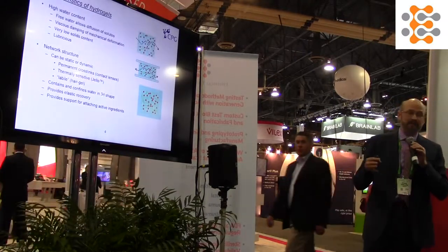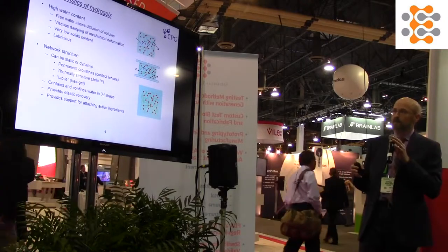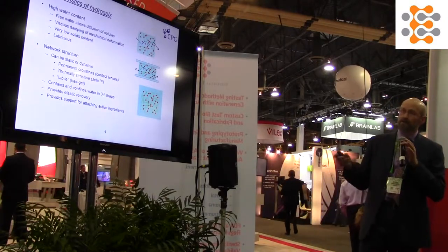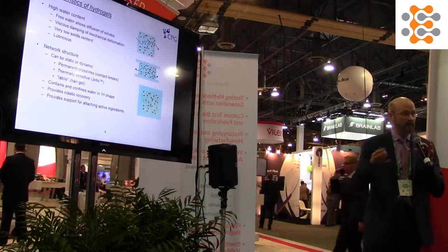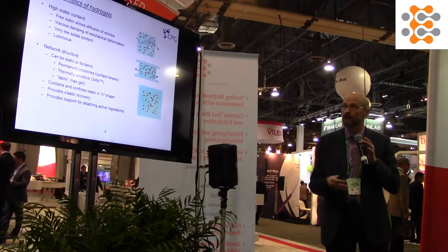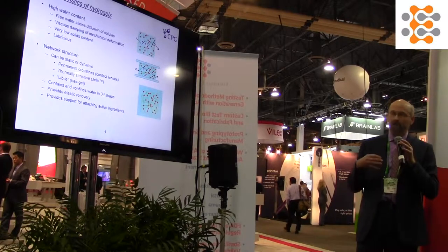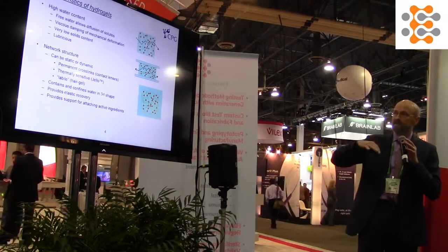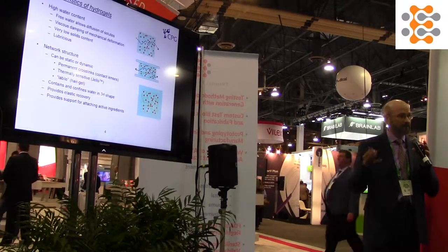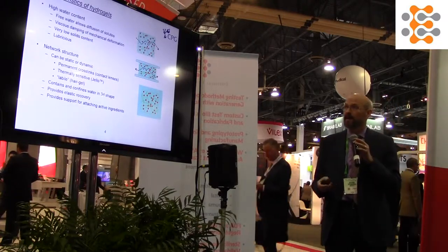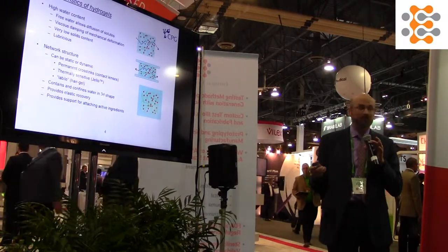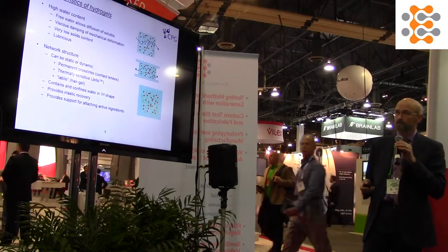The high water content of hydrogels is what really gives it its unique properties. The free water allows diffusion of solutes in and out, which is why it is very good for drug release. The water also acts as a viscous damping effect. So rather than an elastomer, you have a viscous damping behavior, which is why it functions well as a cartilage type replacement. Also, the water content makes it very lubricious, depending on the type of material used.